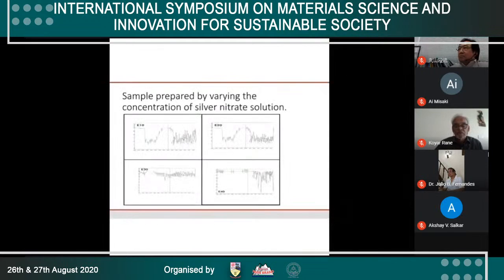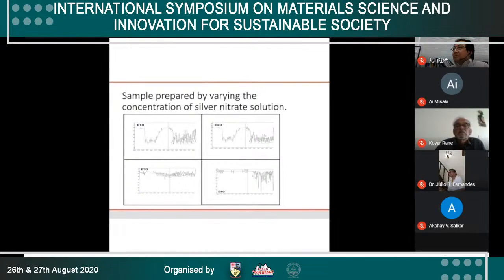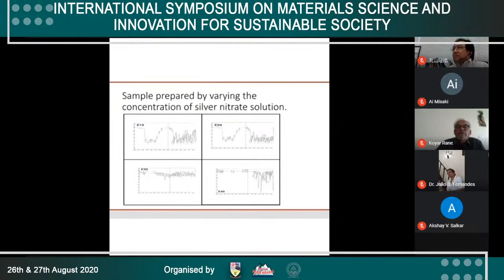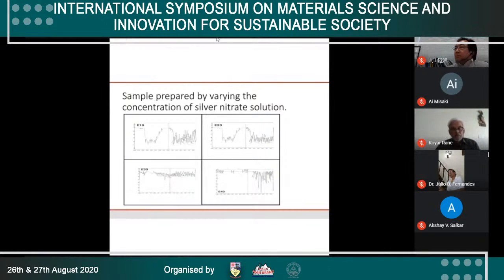And now, these are the spectra of samples prepared by varying the concentration of silver nitrate solution. Here, sample E10 is similar to sample A1. In the spectrum of sample E30, prepared using 30 ml extract, the band at 3670.54 cm inverse represents OH vibration. The band at 891.11 cm inverse represents NH bond. After comparing it with sample E10, we can understand the band representing OH stretch moved to a higher wavelength region.